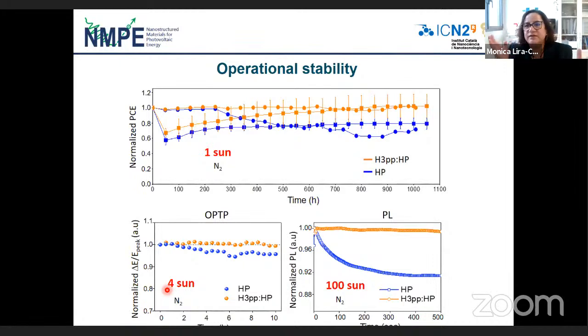It's clear that if we increase the amount of light irradiation, the degradation of the devices and the material will be even harder. You are really stressing the devices and the materials. In this case, even increasing up to 4 sun, 100 sun, we observe that our devices, the orange one with additive, show very stable and reproducible results. So it was very interesting to notice. Now we have to understand what is really happening. How come we are not improving efficiency and voltage, but we have very good stability?